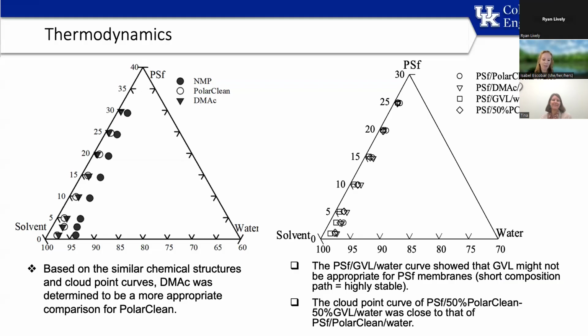Then through a lot of work, a lot of publications that we have done, we determined that ideally, in order to use GVL, as shown on this one, we had issues. There were a lot of issues with using GVL. And as we can see, especially down here in this lower side of the ternary diagram, as we are close here to this 100% water, 0% solvent, we see that the composition path, which is the distance between the axes and the midpoint of the cloud point curve here, is the shortest for the GVL, which means that it is the most thermodynamically stable, which means it's the least likely to be able to form a membrane.